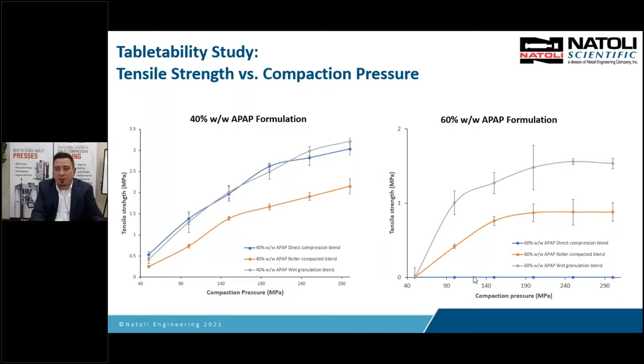Well, look at the roller compacted blend. We didn't achieve our 1 or 2, but we did get a little bit below 1. So if we needed to do roller compaction and hit that 1, we would reformulate a little bit. We can change some of the processes on the roller compactor, roll speed, auger speed, and all this that will influence the resulting tablet strength. But look at the high shear granulation blend, which is the gray. We achieved our 1 at relatively low pressure, and we never achieved our 2 due to this leveling off.